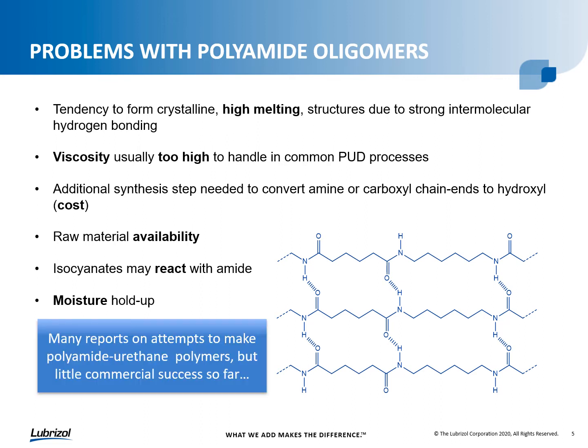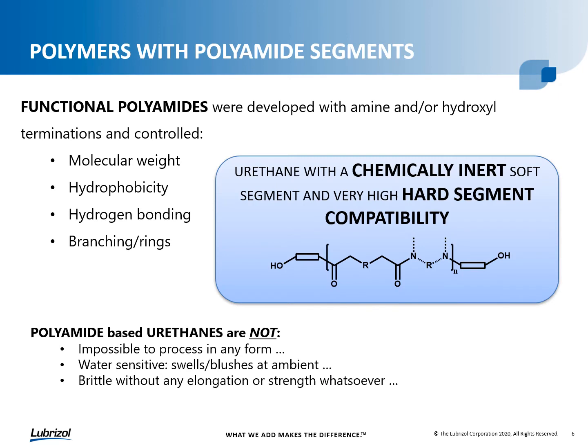So there were many reports on attempts to make polyamide urethane polymers, but little commercial success so far. But Lubrizol's polymer synthesis scientists found a way to overcome some of these challenges working with these polyamide oligomers and develop polymers with polyamide segments. So ultimately, functional polyamides were developed with amine and/or hydroxyl terminations and controlled degrees of molecular weight, hydrophobicity, hydrogen bonding, and branching or rings. And really being able to overcome some of the challenges or misnomers and develop polyamide-based polyurethanes